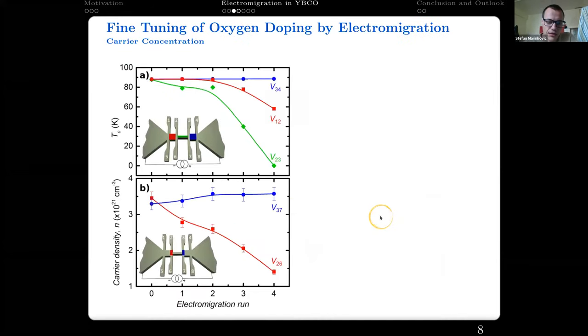Going further, we have compared the change in critical temperature and carrier density by proxy of Hall measurements after several electromigrations. So in these images here, you can see we have performed 4 electromigration runs on one device and have measured first the critical temperature. In the green is the central bridge, red is the cathode side, and blue is the anode side. And we have compared at these 2 points the carrier concentrations gained by Hall measurements. And as you can see, the carrier concentration drops on the cathode side and slightly increases on the anode side, while the critical temperature drops most rapidly in the central part and a little slower in the cathode side.